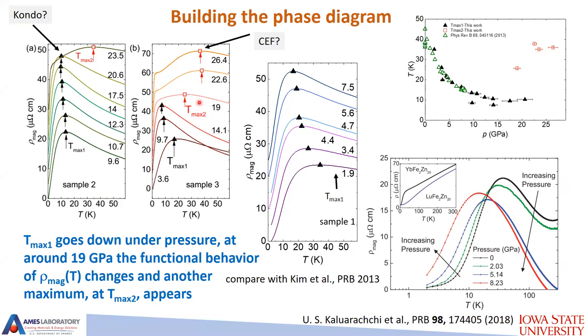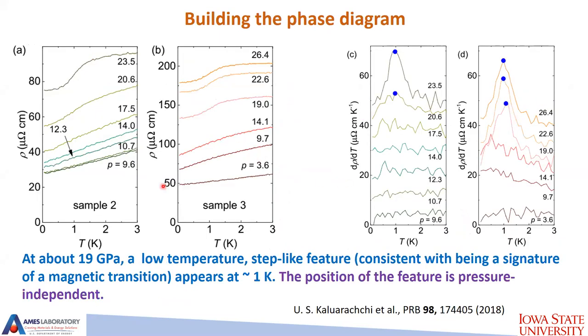Then somewhere around 19 GPa or so, this maximum has a different shape and width and jumps to a different temperature. Fine, is it all? Actually not. In two runs which went beyond 19 GPa, we had a step-like feature at low temperatures at pressures above 19 or 20 GPa. The width is actually below one Kelvin. It looks like a signature of a phase transition, possibly a magnetic transition. It's around one Kelvin, and it does not move when you go from 19 GPa to 26 GPa. It stays more or less the same.